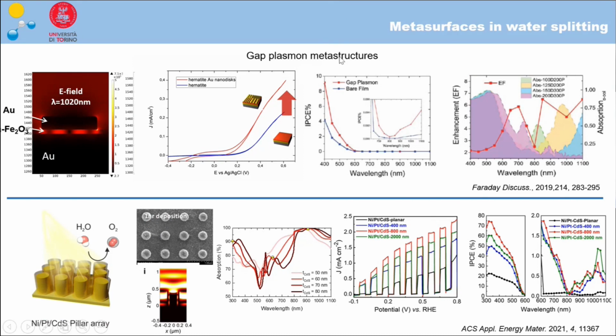And here are some examples of how we use metasurfaces for catalysis. These are two examples of the use of plasmonic metasurfaces for photoelectrochemical water splitting cells. We use these devices as photoanodes, for the oxidation reaction. In the first case, we sandwich a semiconductor used for this kind of application, like hematite, between a gap plasmon structure, meaning we are able to squeeze light between a mirror made of gold and small nanostructures on top of the hematite film. And this geometry can bring a doubling of the photocurrent if we compare it with the planar hematite film.